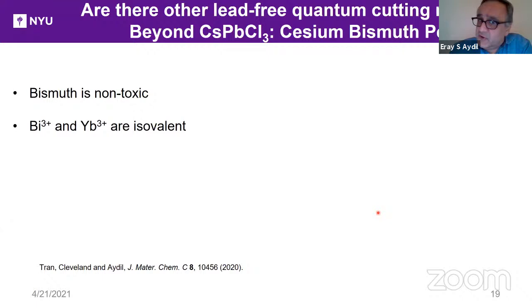So we started asking, are there other quantum cutting materials? In particular, are there lead-free quantum cutting materials? Is that particular defect really specific, or would any defect near two ytterbium ions do? So beyond cesium lead chloride, we started looking at cesium bismuth perovskites. And of course, bismuth is non-toxic, so that's one reason to go there. And it's an alternative where now bismuth 3 plus and ytterbium 3 plus are isovalent, so you might be able to put more ytterbium into the system. And it's also a test for whether this charge compensated defect is necessary, or would any defect do, like a bismuth vacancy.